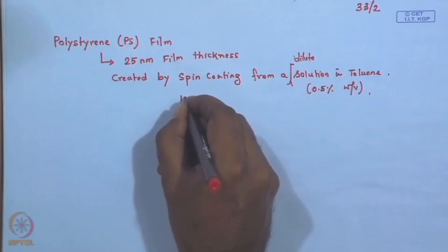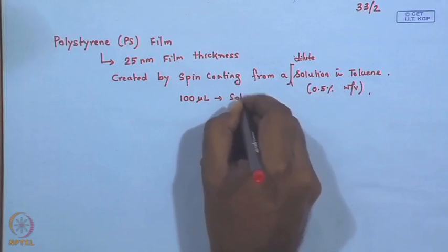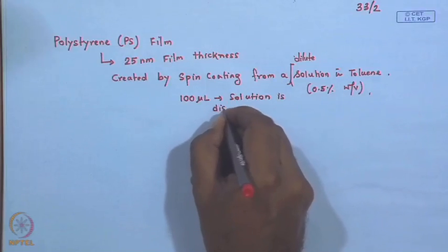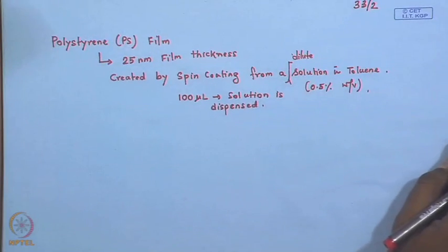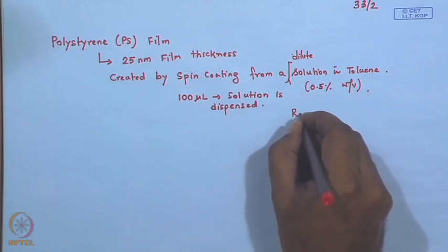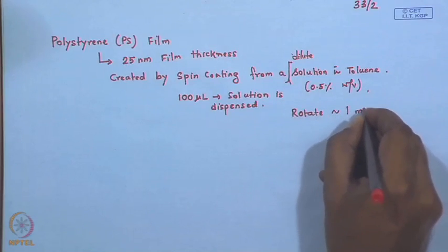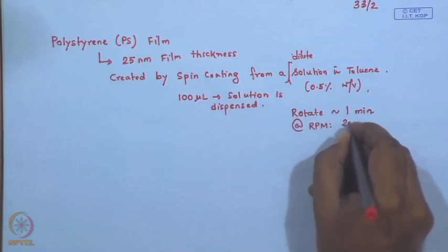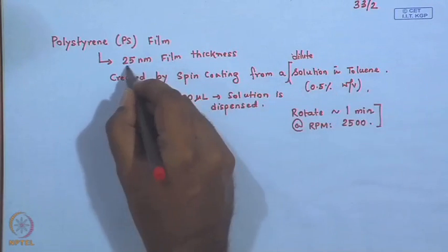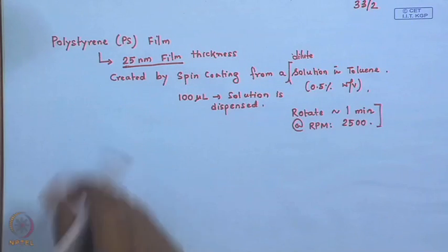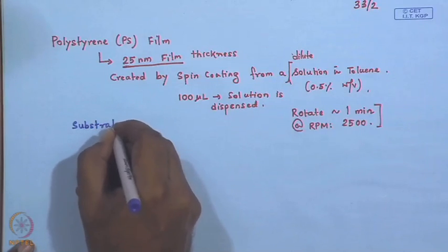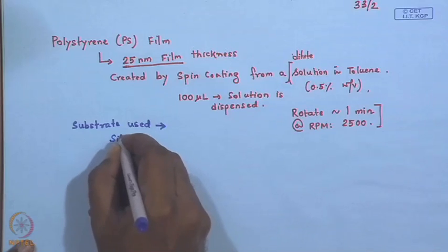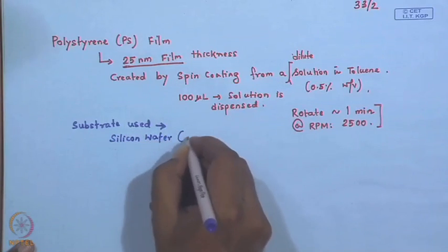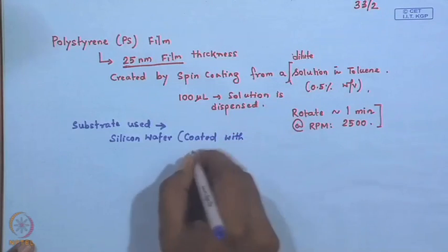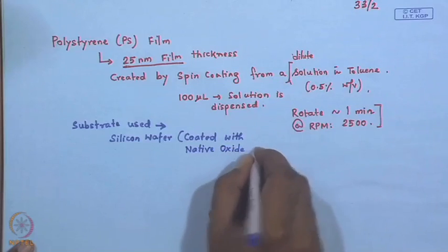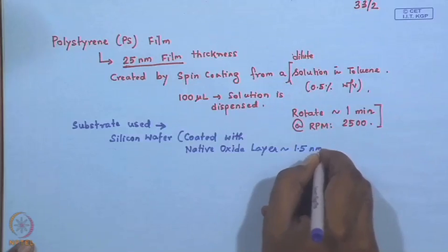Typically 100 microliter solution is dispensed. We have talked about spin coating in greater detail, so each one of these parameters should make sense to you. 100 microliter solution is dispensed, and then typically you rotate for 1 minute at an RPM of 2500 to get this type of 25 nanometer thick film. Just would like to highlight the substrate used was a silicon wafer coated with a native oxide layer, the thickness of which is 1.5 nanometer.